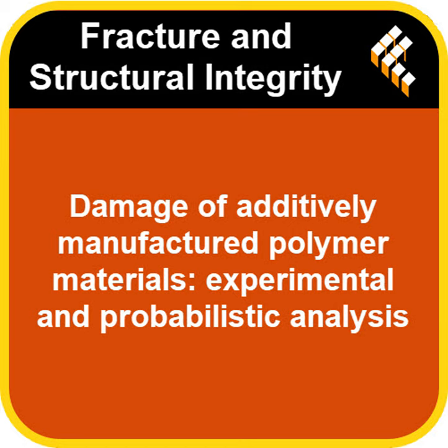By removing the crack before it hits that critical unstable stage, you get rid of the stress concentration point. You eliminate the stress concentration at the crack tip, you physically halt the crack propagation because the crack isn't there anymore. Right. And you significantly enhance the part's expected durability and structural integrity, especially if it's operating in challenging conditions where that crack might otherwise grow quickly to failure. That's a fascinating idea. Moving from just predicting failure or designing to avoid it to actively preventing it based on monitoring and these predicted damage thresholds. It really shifts the paradigm, doesn't it, from purely reactive replacement towards potentially proactive maintenance or intervention for critical components.